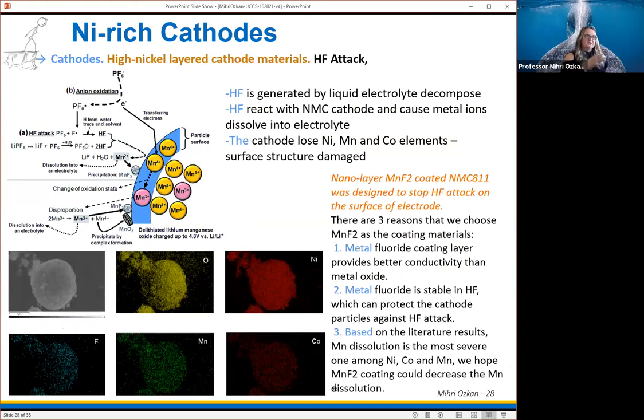And more recently, there is a trend to move towards cobalt-free, as I mentioned, because of the cost, cobalt-free or low cobalt type of cathodes. This is moving and replacing cobalt with nickel, making nickel-rich cathodes, and they are very high performance cathodes. There are standing issues with that. A very strong acid, hydrofluoric acid, is formed during the cycling, and that decomposes the electrode and causes the electrode metals to dissolve into the electrolyte. That creates lots of structural issues and damage.